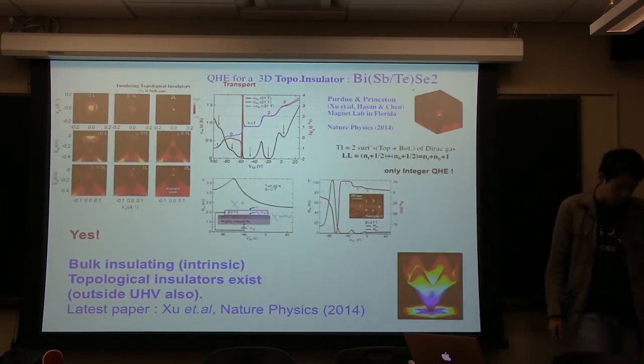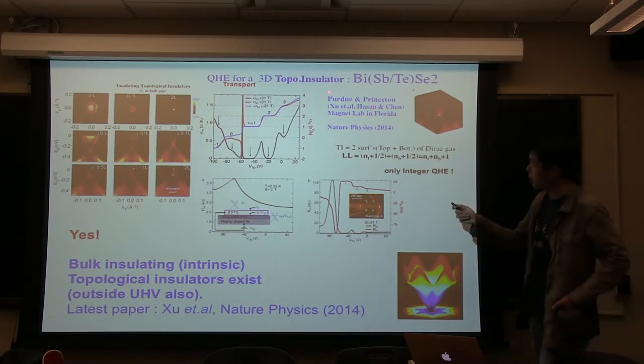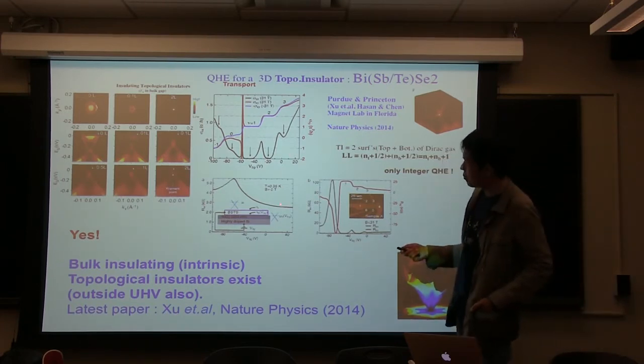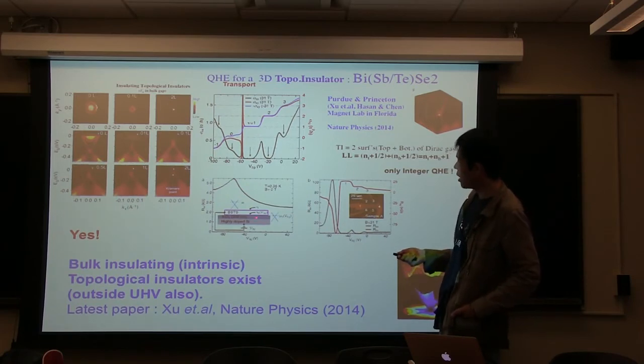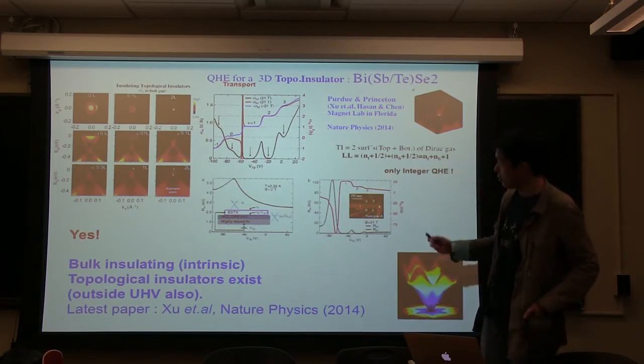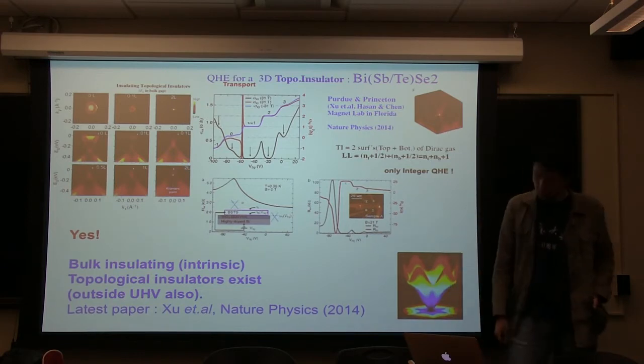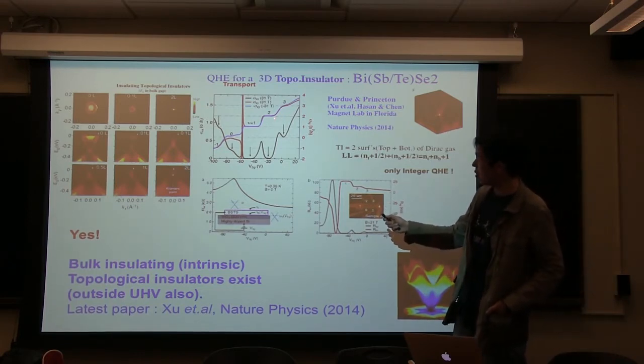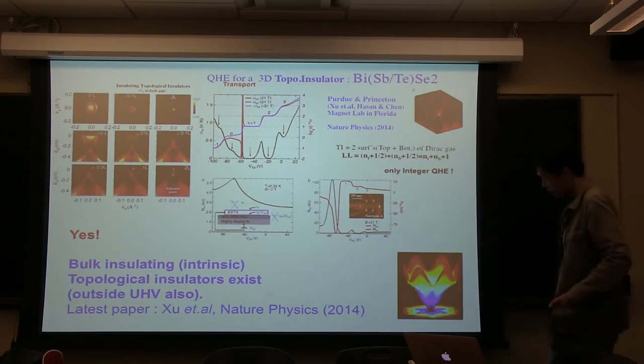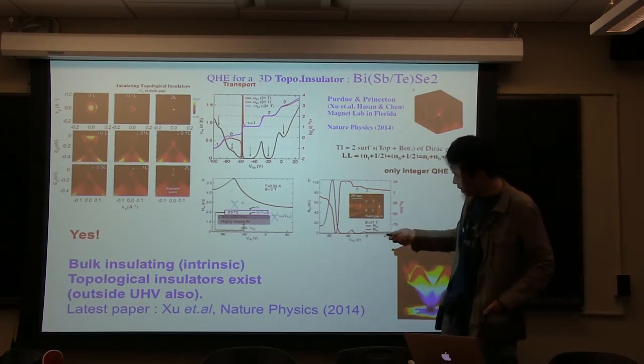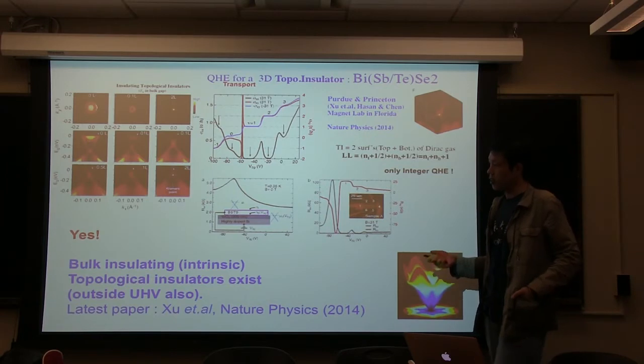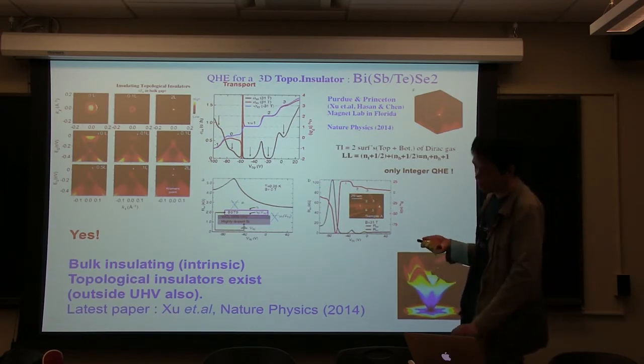One recent advance I want to point out is that in collaboration with Professor Chen's group in Purdue, we discovered a compound: bismuth antimony tellurium selenium, BSTS. In contrast to previous topological insulators, this compound is truly bulk insulating, and the surface also has high enough mobility so that we can see very well-defined plateaus arising from quantum Hall states from the topological surface states. This means the sample BSTS is really in the topological transport regime, and one can test device applications for 3D TIs using this sample.